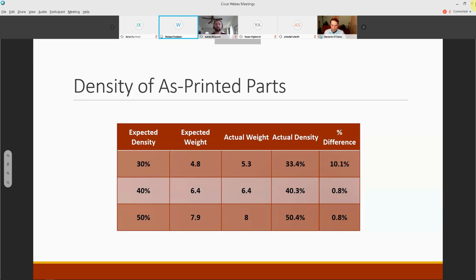Shown here, the 30% actual weight was off from the expected weight after printing, and this is due to excessive residual powder stuck on the part. We also turned the parts on the lathe, so we might have removed unsupported, uneven structures.